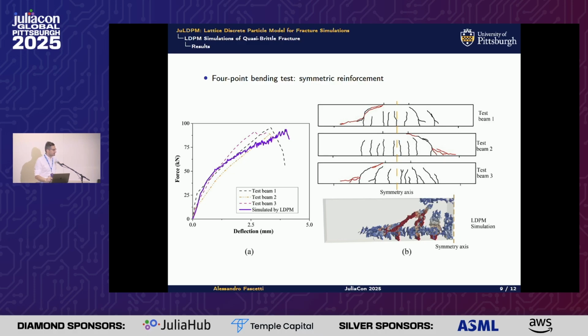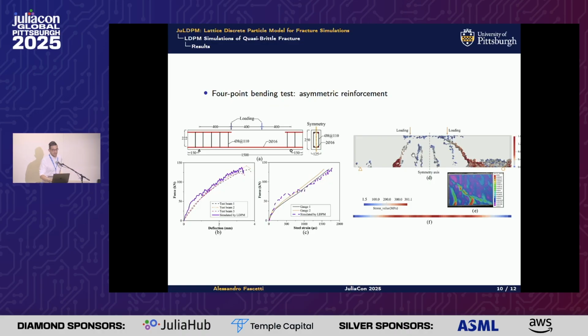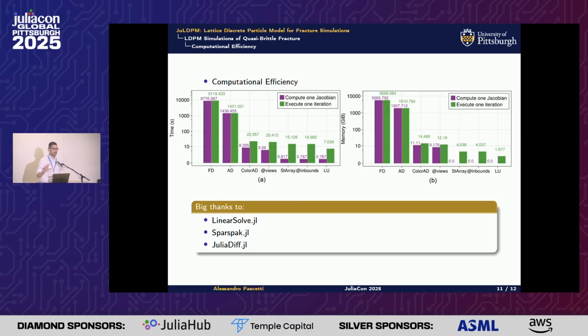Then just a couple of very, very quick results. We are able to simulate and replicate very complex fracture patterns. This is a 4-point bending test under symmetric reinforcement conditions and non-symmetric loading conditions. You see here a DIC, which is digital image correlation, that provides you with a strain map in 2D, and you see that, of course, we can represent such very complex fracture patterns particularly accurately. And here I have some computational efficiency analysis, granted by a lot of fantastic work. Particularly, the package uses LinearSolve, Sparspak.jl, JuliaDiff, some of the JuliaSim, and some of the automatic differentiation tools that are available in Julia, which were a fantastic help in the development of this.